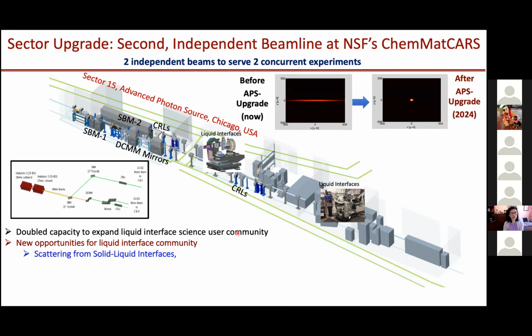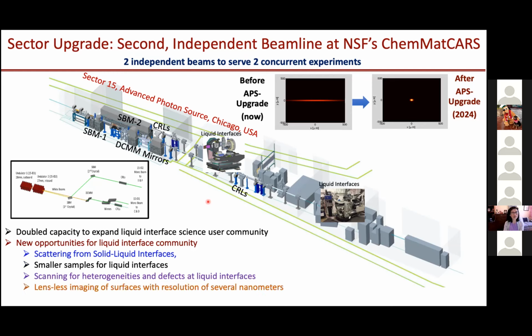For example, we can scatter from solid-liquid interfaces—this is what the new diffractometer will do. With a smaller beam, we can work on smaller samples and scan the inhomogeneity and defects at that interface. With a more coherent beam, we can possibly do some coherent imaging, and with higher energy flux, we can enhance the scattering from buried liquid-liquid interfaces.